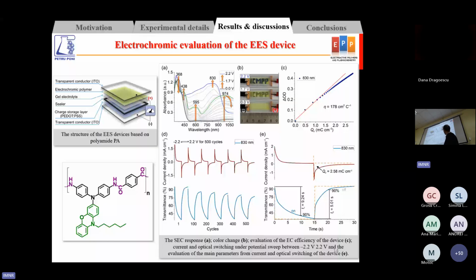With the increase of the voltage, the polymer started to change color from transparent to green and then to blue. Also, the main electrochromic aspects were evaluated, including the efficiency, which is good but low due to the high viscosity of the electrolyte used. These aspects also make the time response longer. Also, we tested the stability up to 500 cycles.